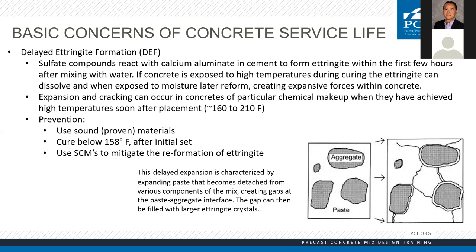You may have driven by bridge abutments and seen cracking with white stuff pouring out. We've traditionally said that's ASR, and that is what ASR looks like. But when we're doing mass concrete with high heat of hydration, that's most likely delayed ettringite formation. That can happen in precast pieces too. What causes it? Typically it's the heat of early curing.